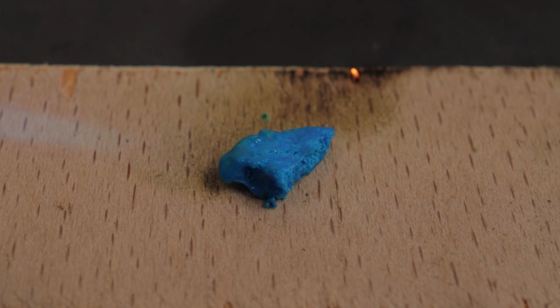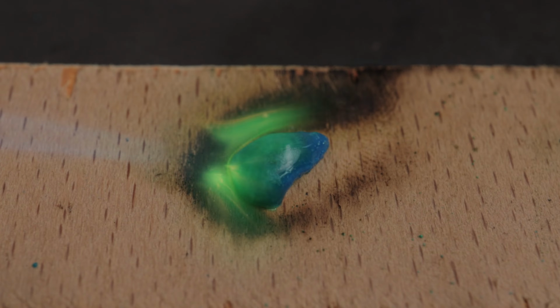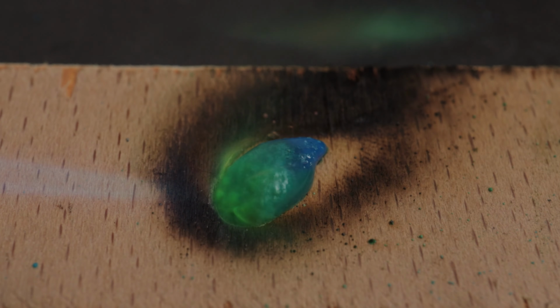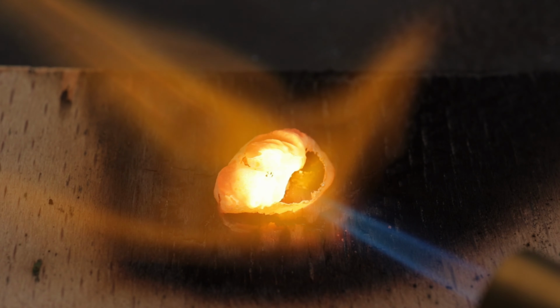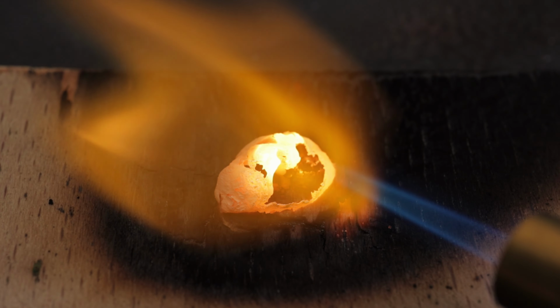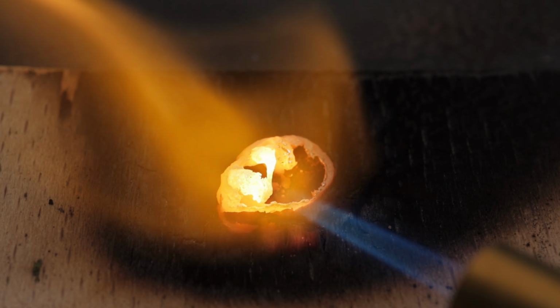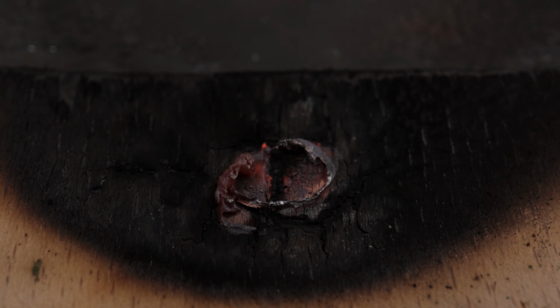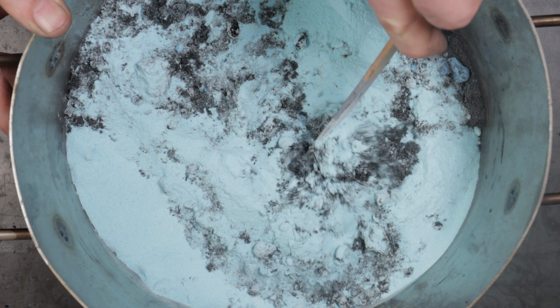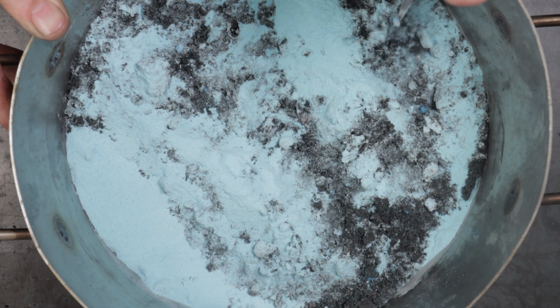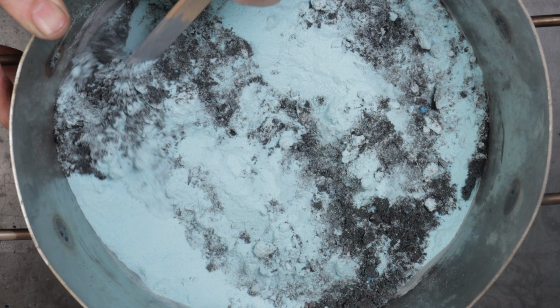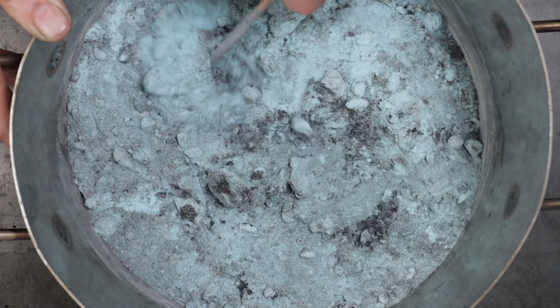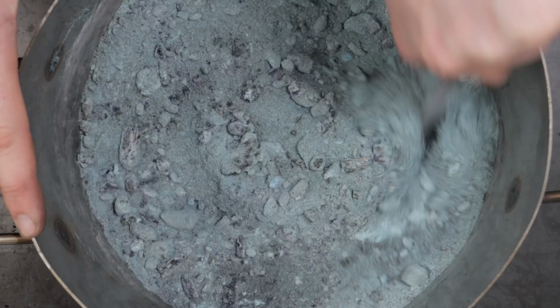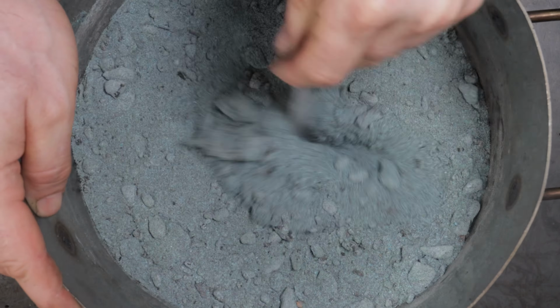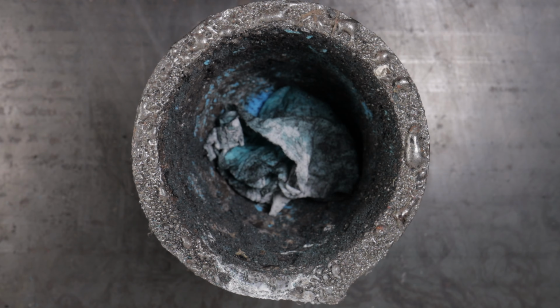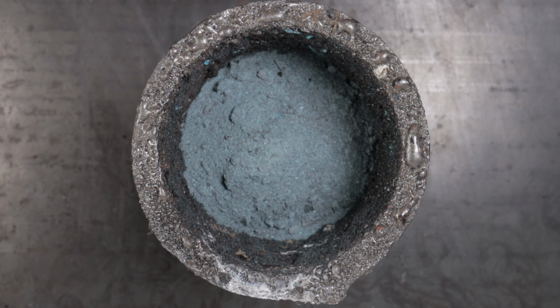I did a little flame test. See the green color? That's an indication of copper present. And here we have metallic copper. I did the first batch together with charcoal as a reducing agent that liberates copper from oxygen. But it's better to add charcoal later on, otherwise you risk that some sulfur will be trapped within the copper.